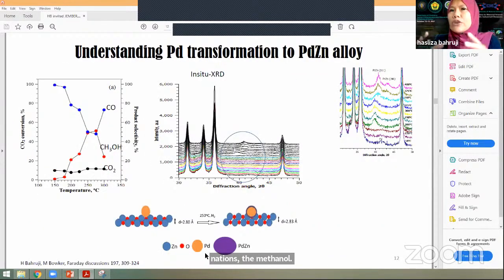So we try to understand the transformation of palladium on zinc oxide to palladium zinc alloy by carrying out an in situ experiment. Basically, we start with the palladium on zinc oxide catalyst at 150 degrees Celsius, and then we slowly raise the temperature up to 300 degrees Celsius, and then we monitor the conversion of CO2, the black dots here, the selectivity towards CO, which is the blue dots here, and the selectivity towards methanol, which is the red dots here.